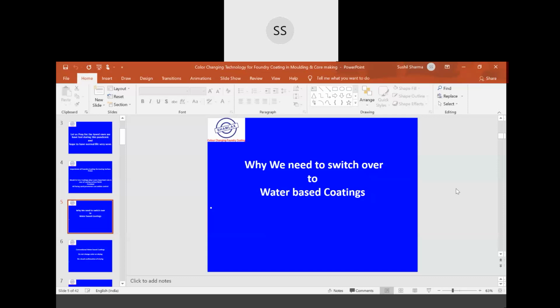But if the foundryman starts using solvent-based coatings with resin sand systems, there are different types of problems a foundryman can face. See, the problem is that when you ignite the solvent-based coating, the heat generated during the solvent burning is so high that the surface bonding of the sand particles becomes weak. This heat is sufficient to weaken the particle bond. And when liquid metal enters the mold, the surface sand particles try to erode and move away from each other. So many times we get sand inclusions or a rough sand surface finish in the cast. That is the reason a foundryman needs to switch over to water-based coatings whenever they have modern resin sand systems.